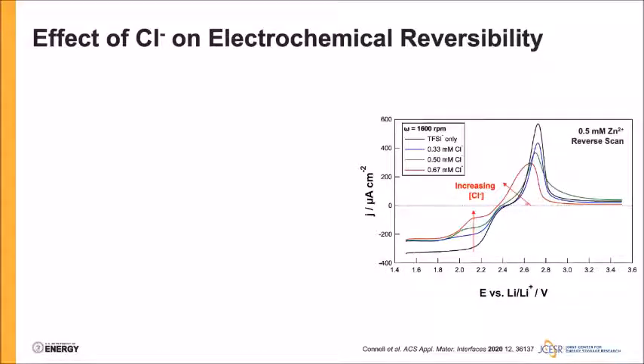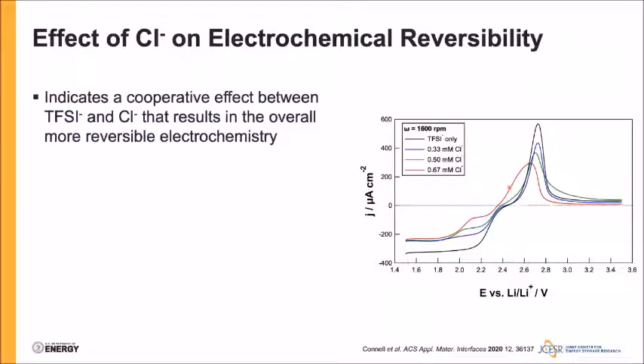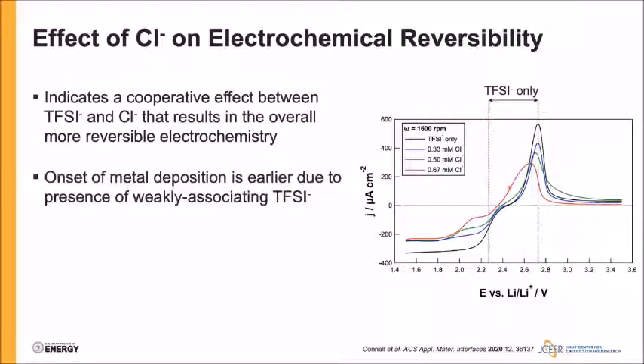Correspondingly, as we increase the chloride concentration, we see the onset of metal dissolution shift to lower overpotential. And so what this suggests is a cooperative effect between TFSI and chloride that's resulting in the overall more reversible electrochemistry in this system. To illustrate what I mean by that, we can return to this idea of there being essentially two overlaid redox couples. If we highlight the TFSI-based contribution to the voltammetry, we see the early onset of metal deposition, but a higher overpotential for metal dissolution.